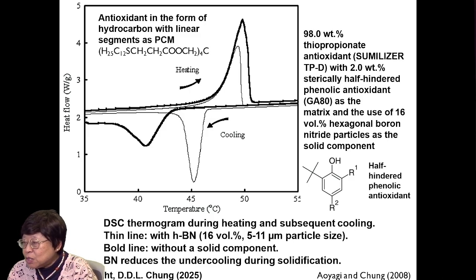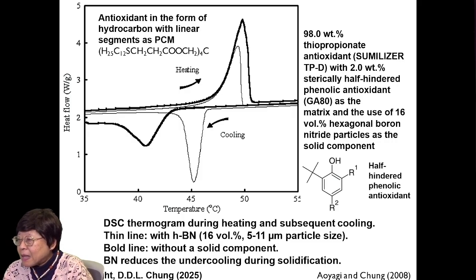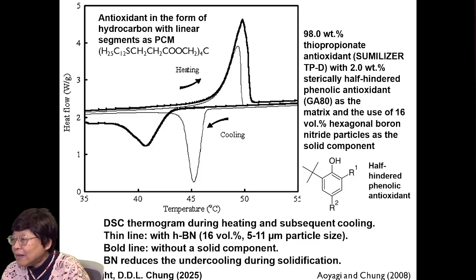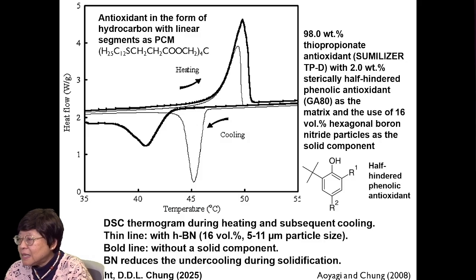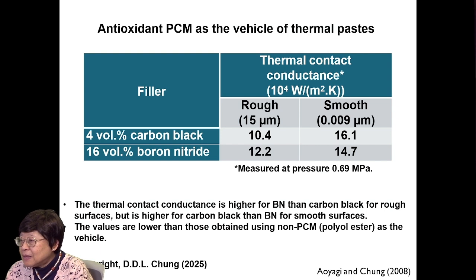This is the DSC thermograms during heating and subsequent cooling. The thin line is a phase change material with boron nitride filler, and the bold line is without the filler, and the boron nitride reduces the undercooling during solidification, and that's good. And this particular phase change material is 98% weight thiopropionate antioxidant with 2% weight sterically hindered phenolic antioxidant as the matrix. And this antioxidant PCM as the vehicle of the thermal paste gives these values of the thermal contact conductance.